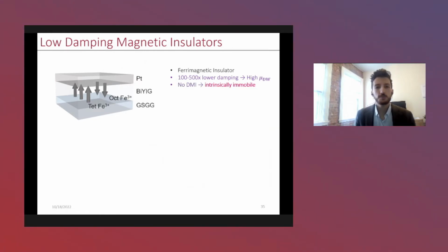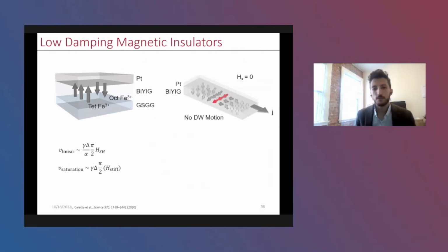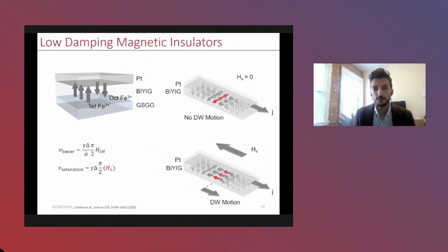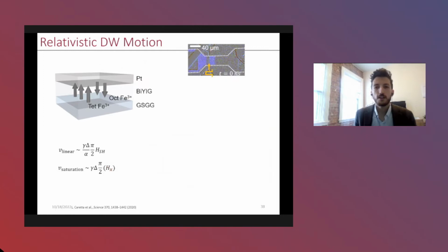The challenge with this material system is that it's pretty difficult to stabilize the DMI in this material. We've had pretty bad luck stabilizing Néel-type domain walls. So the domain walls are actually intrinsically immobile. They're the wrong type. They're Bloch, not Néel. However, we can get around this, kind of cheating in some ways, by applying a small in-plane field to the sample to reorient this Bloch domain wall to a Néel configuration. This field is larger than the domain wall anisotropy, but much lower than the bulk anisotropy of the film, the PMA. And so this is exactly what we did.